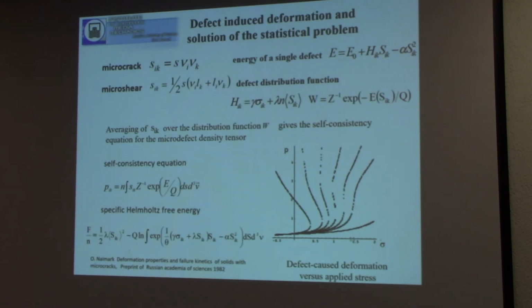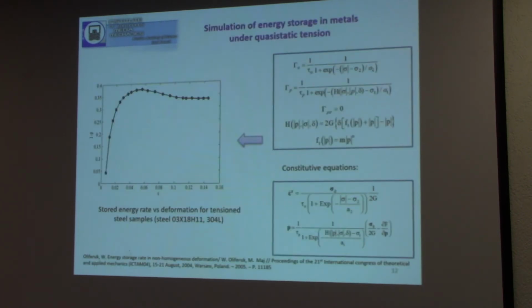So we have practically two different ideas. We have experiments with stored energy, and we have a statistical theory of defects, and we try to simulate the stored energy evolution under plastic deformation. In the simplest, one-dimensional case, we can use special equations for kinetic coefficients, and finally you can see the simulation of the results of Professor Oliferuk, the experimental and theoretical results of stored energy evolution under plastic deformation, under tension of steel.